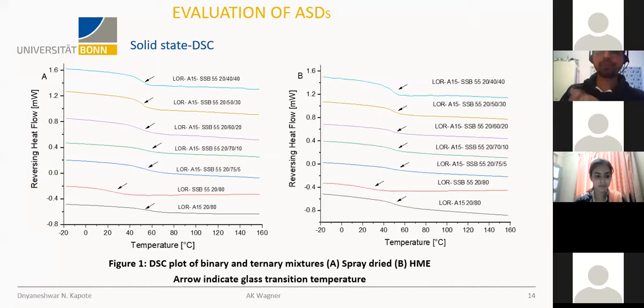While in the case of the other ternary mixtures, the glass transition temperature was decreasing based on the shellac concentration. So in the case of loratadine, Affinisol, and shellac in 20-75-5, the glass transition temperature observed was 59 degrees Celsius, while in the case of 20-40-40, the glass transition temperature decreased to 50 degrees Celsius. This indicates that with the decrease in the glass transition temperature, the API is homogeneously mixed into the polymer matrix, leading to increased interaction. Thus, it's a sign that they are miscible with each other.